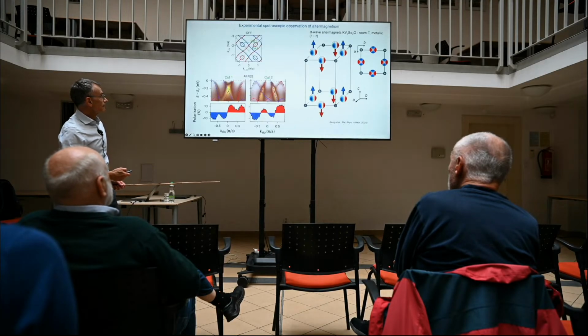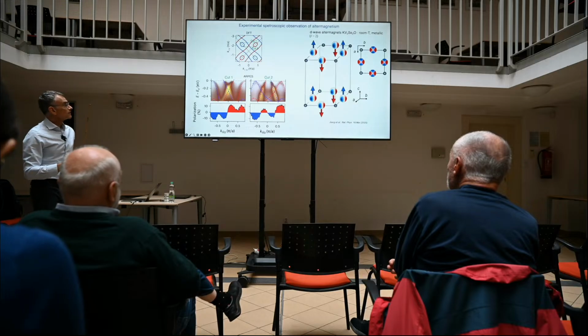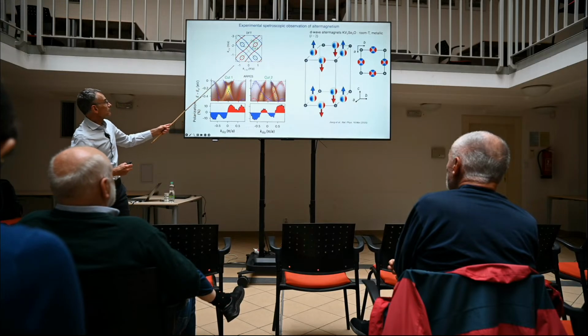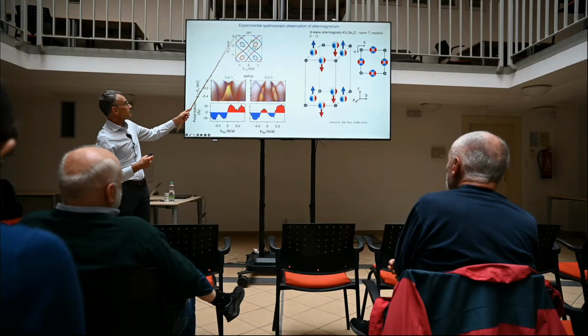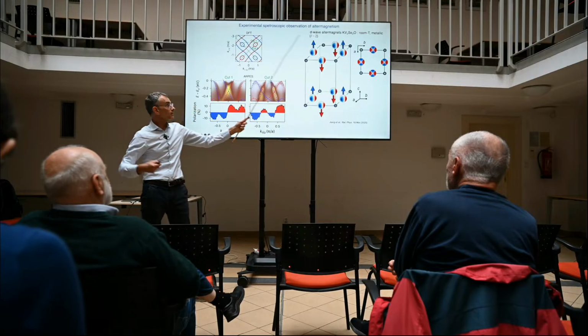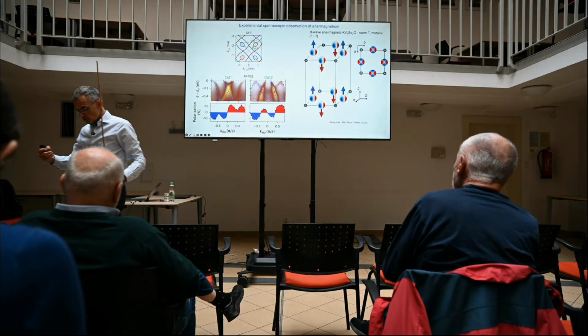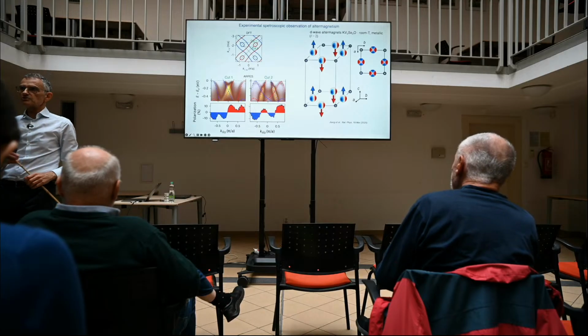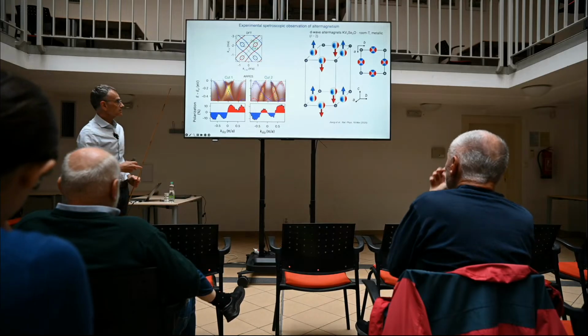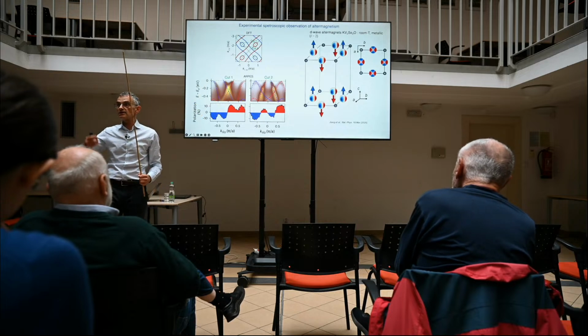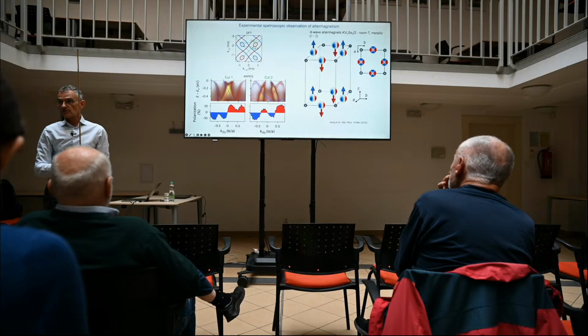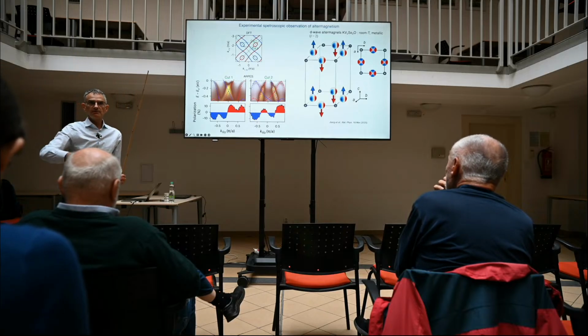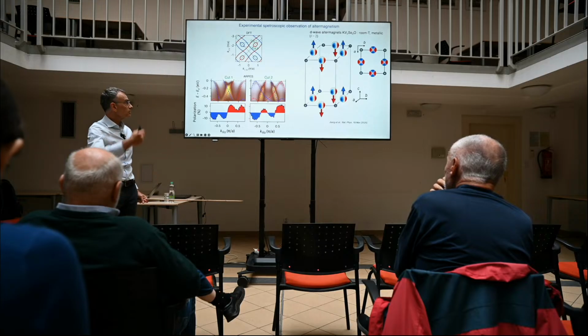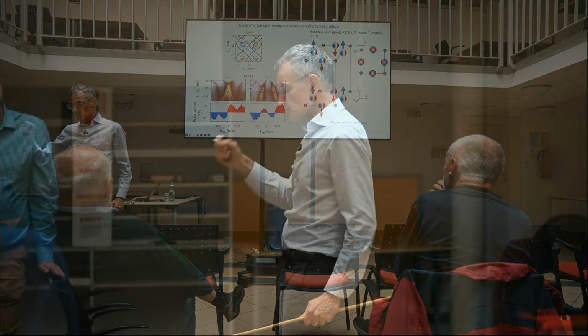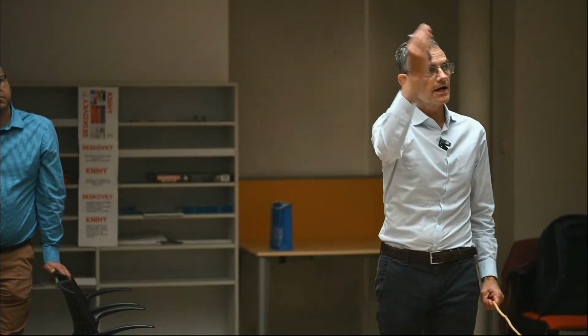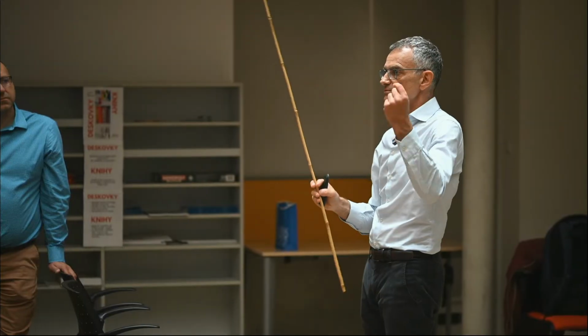For example, here. This is a Fermi surface of a very nice altermagnet, which has exactly the same crystal structure as the model one. It is almost in textbooks how you do DFT calculations and angle-resolved photoemission when you want to understand spectra of your material. You just look at high symmetry planes, high symmetry lines, high symmetry points in your Brillouin zone. There are standard procedures that people were following for decades and decades. How am I going to do these spectroscopy measurements and corresponding density functional theory calculations? Go along the high symmetry planes, go along the high symmetry lines and high symmetry points, see what you see.